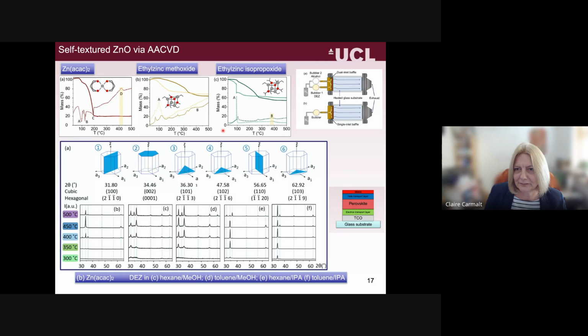Now it is interesting looking at the precursors themselves. So this over here was the precursor I just talked to you about, the ethyl zinc isopropoxide. I mentioned that you can use zinc acac as well, and we also compared it to ethyl zinc methoxide. Now these two are quite interesting because you can either make the precursor as shown here, isolate it, dissolve it into a solvent, and then do the aerosol assisted CVD as I've talked to you through before.